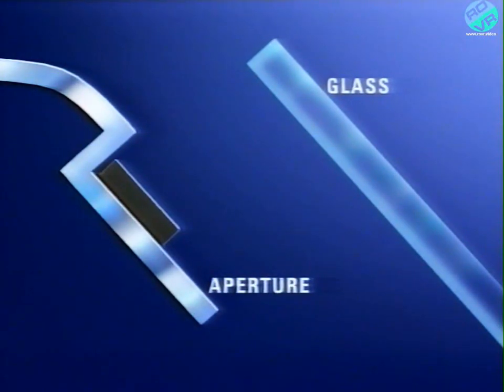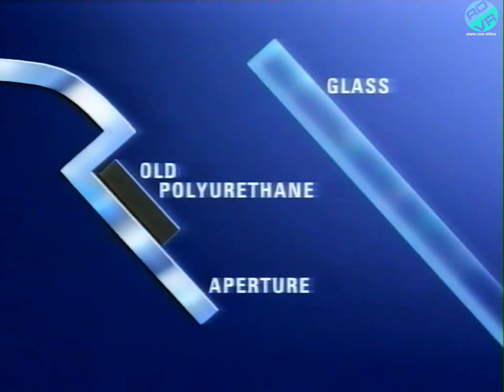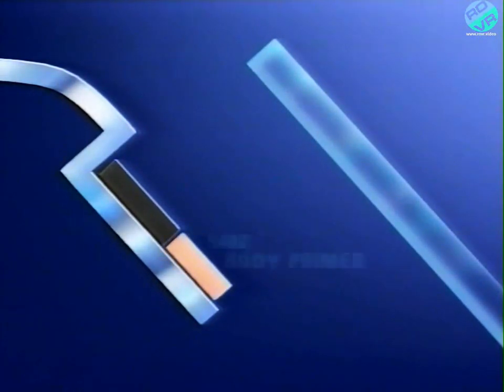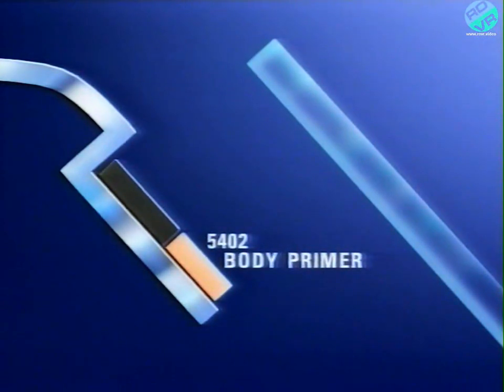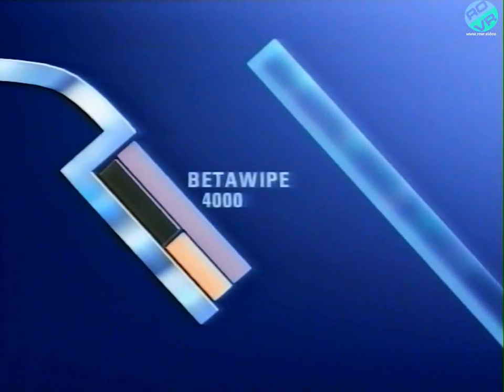When a screen is removed, the cutback layer of old urethane remains to form a bed for the new glass. Any areas where painted metal is exposed should first be cleaned with BetaClean 3500 and then have 5402 body primer applied. This product ensures that, irrespective of the type of paint process used by the manufacturer, there will be good adhesion for the polyurethane. BetaWipe 4000 is then applied to the surface of the aperture. This pre-activates the old polyurethane and ensures good bonding between the old adhesive and the new.